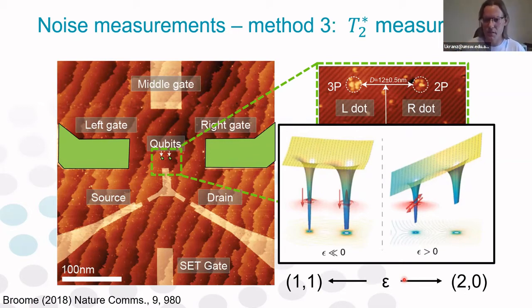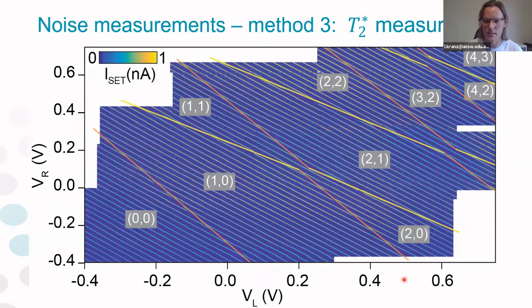This is the charge stability diagram of our device. The diagonal lines correspond to the SET lines or Coulomb peaks, so every line is like adding 1 electron to the SET. We can also see breaks in the SET lines that arise as we add electrons to our qubits, because that effectively shifts the potential of the SET as well. By analyzing this charge stability diagram, we can figure out how many electrons we have on the qubits in every region. For example, if we apply negative voltages, we can deplete our double dot system.